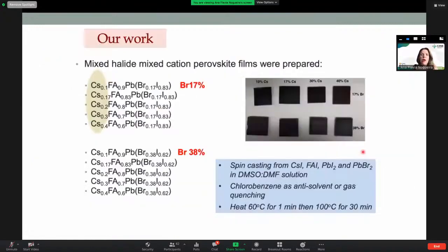We have been working with perovskites containing different ratios between iodide and bromide. You're going to see toward the end of my talk that we work with two concentrations of bromide, 17% and 38%. We also change the cesium concentration, sometimes from 10% to 40%. So these are the films that you can get after finishing the experiment.